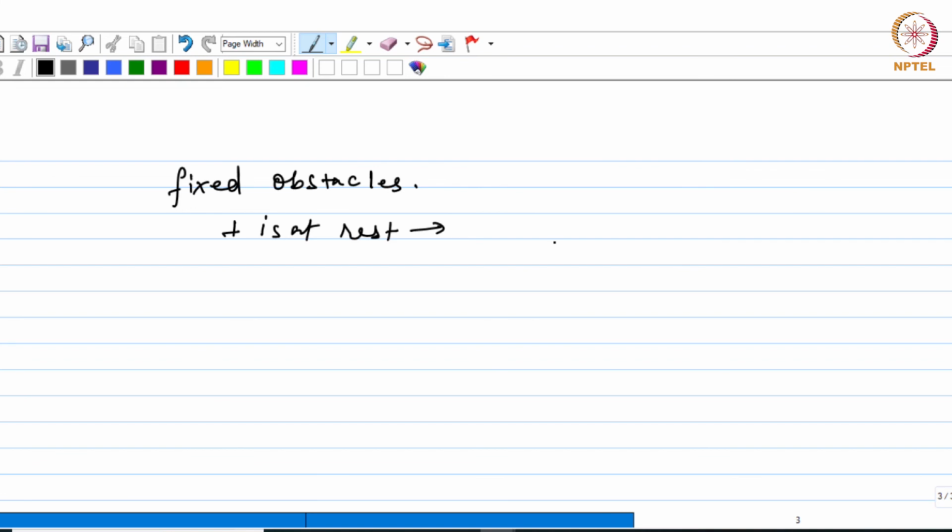So now if you provide some velocity to the dislocations, the distance between the atmosphere and the dislocations will increase, and the distance of separation will increase with increasing velocity.